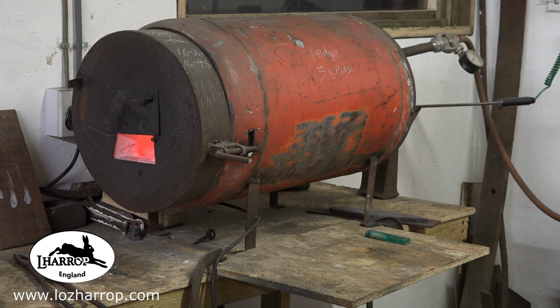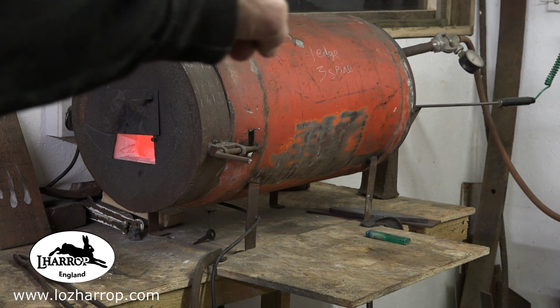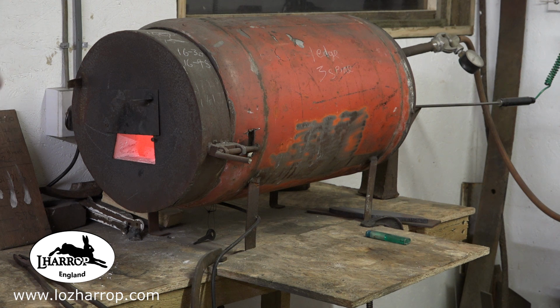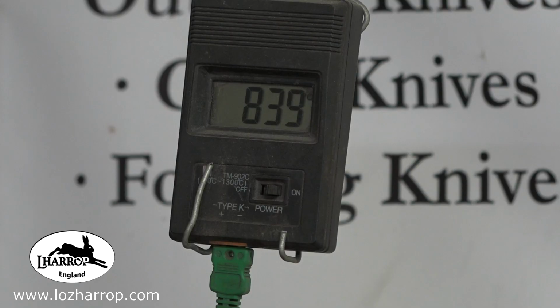To do that, it's called normalising. And what we do is we heat the knife up to a specific temperature. In this case, it's way above non-magnetic, 850 to 900 degrees centigrade. We heat it up to that, we hold it for a couple of minutes, and then we just let it cool in the air. And I do this 3 times, so the first will be, say, 900, the second will be 800, the third will be 700. Sometimes I'll do 650 or something like that, but I'm just going to do 3 cycles on this, and it's been in there now. It's just about ready to pull out and air cool.